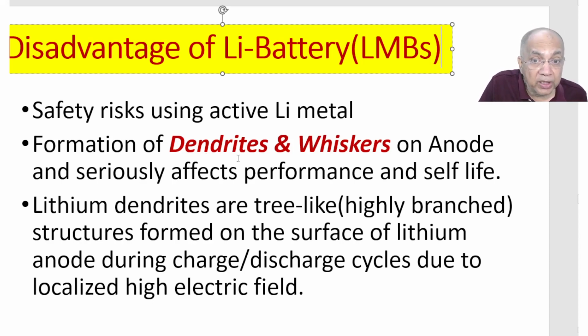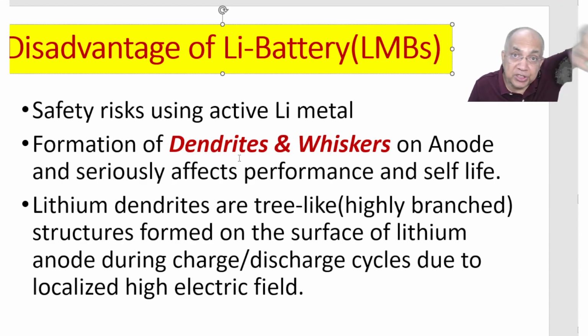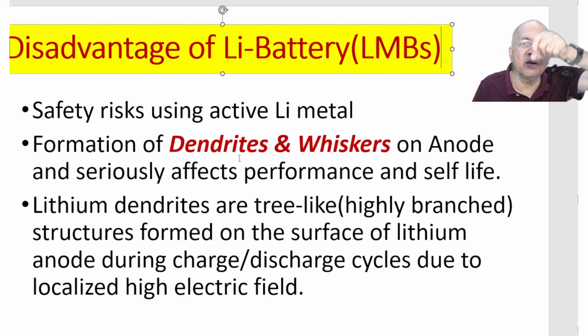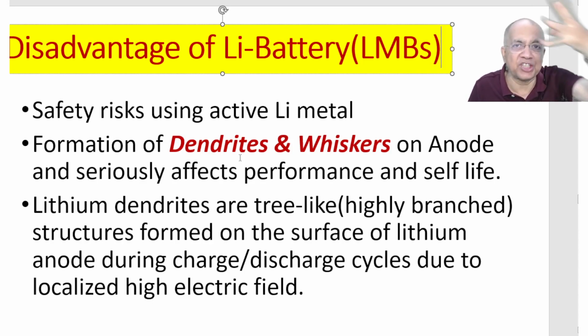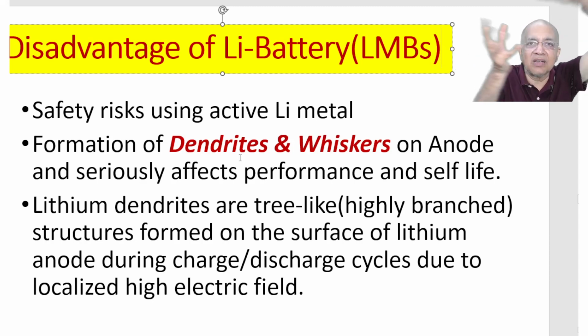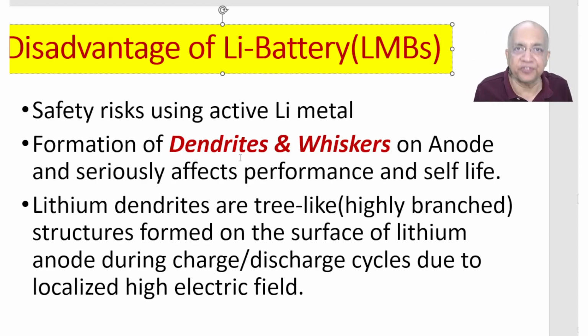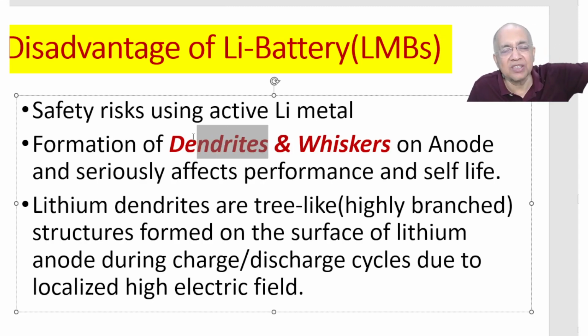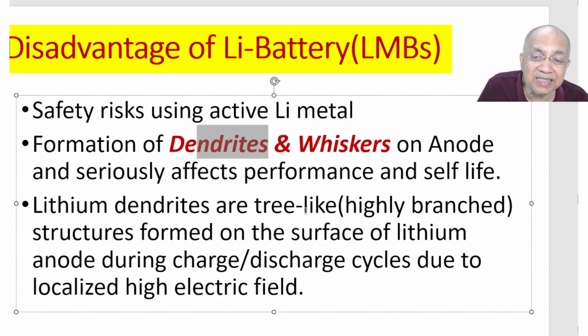And most importantly, when lithium is deposited in the charging mode, it will not be deposited in an even, smooth manner. It will be deposited in an uneven manner to produce projections, some branch-like projections from the anode surface, and those are called dendrites. And if single projections, they are called whiskers. So dendrites and whiskers are formed during the charging process.